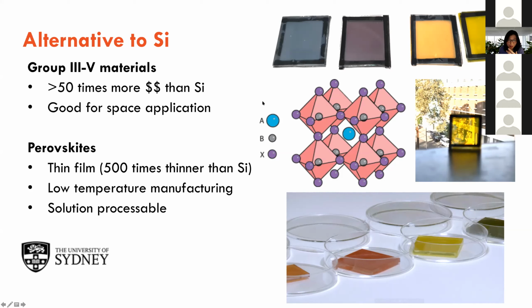Perovskites have this crystal structure. A is the cation. It can be organic or inorganic. The world record efficient solar cells use a hybrid version where the cation is organic. Then the B site is where the metal is, so it can be lead or tin. And then the purple is the iodide, bromide or chlorine. So it's a hybrid organic-inorganic metal halide perovskite. This is the perovskite that has been capturing people's imagination and research attention. Thousands of people have been working on this material for solar cell applications and LED applications.